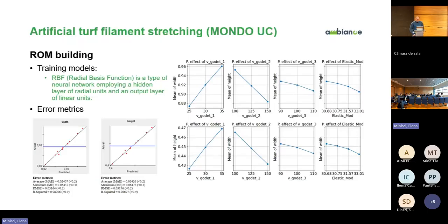That means we need to build a model that is much quicker than the full simulation model, but retains the important results, the ones that we want to use afterwards. In this case, for example, we have two results: the height and the width of the filament, and how they depend on the godet velocities. Analyzing this type of graph, we are able to say which variables are more important, which have the most effect, and which are less important. And not only the importance, but also the trend, in which direction they affect the result.